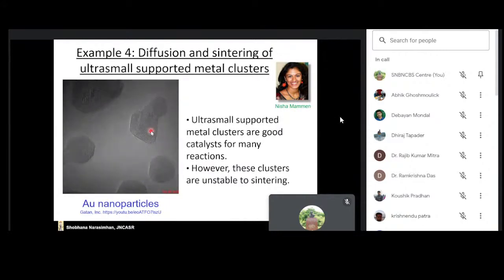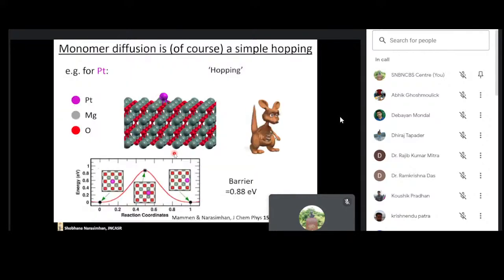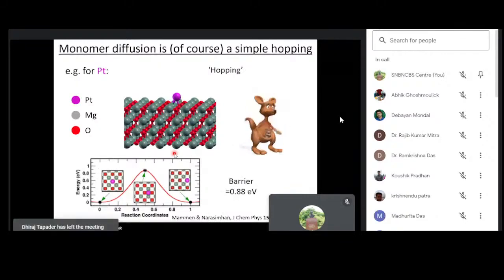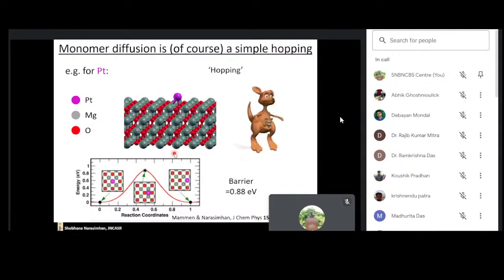This kind of process shown in this video is what's called particle migration coalescence. But you can also have processes where one atom at a time is added to a nanoparticle and it grows by such a process. So the first thing we studied is how nanoparticles move. And we found that the process by which they diffuse, by which they move, is extremely sensitive to the element that the nanoparticle is made of, and also to the number of atoms that the nanoparticle is made of.